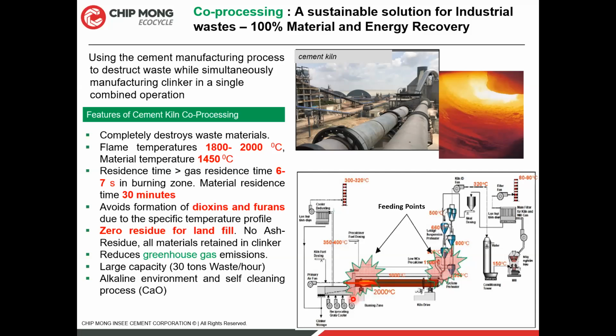If you look at the cement kiln layout, in our main burner we have 1,800 to 2,000 centigrade of temperature, which in layman's terms is one third of the sun's surface temperature, and inside, the material temperature is 1,450. If you compare with the incinerator, the numbers are 800, 900 centigrade, some incinerators are 1,100. So the cement kiln has a much higher temperature, which is a perfect environment for waste disposal. And the second thing is the residence time.